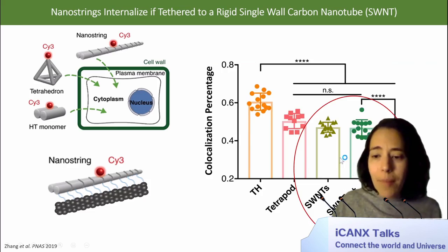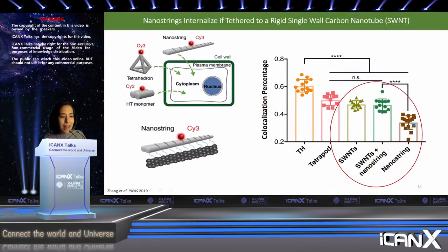What we see is that carbon nanotubes, as I mentioned before, internalize quite well as measured by colocalization analysis. Nanostrings largely do not. And the nanostring plus nanotube complex internalizes just as much as carbon nanotubes. These are interesting results because this complex is much larger than either construct by itself. But the main difference between nanostrings and carbon nanotubes is in their tensile strength, where carbon nanotubes are several orders of magnitude stiffer than our nanostrings, suggesting that stiffer or more compact nanoparticles are also a feature of merit that increases the internalization of those particles across the cell wall.